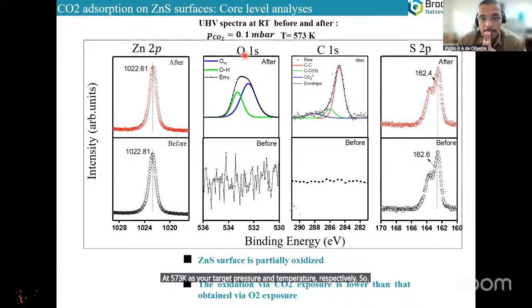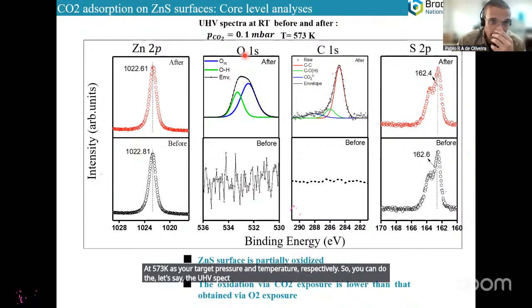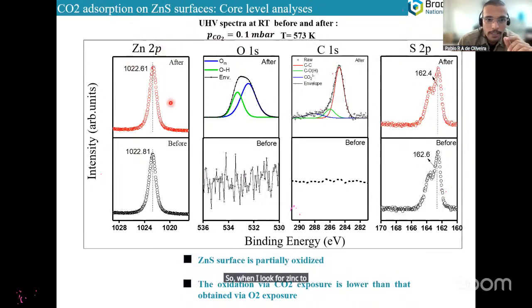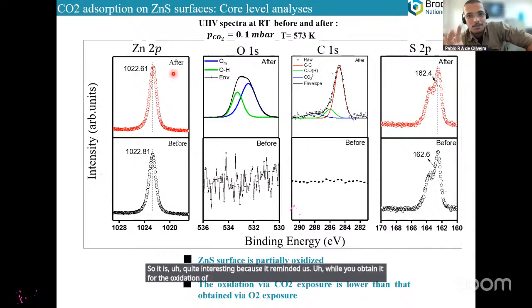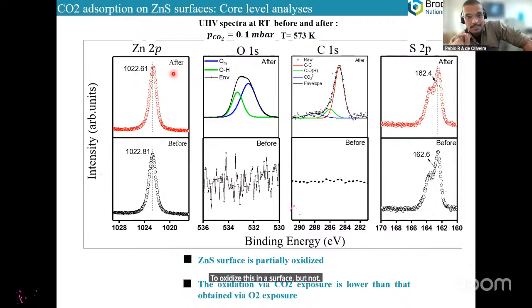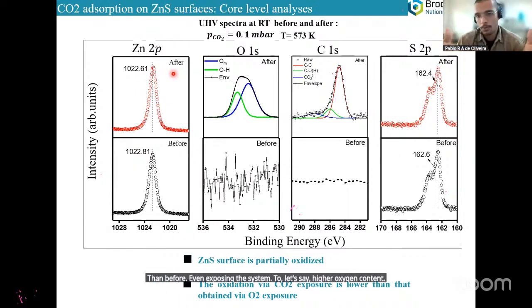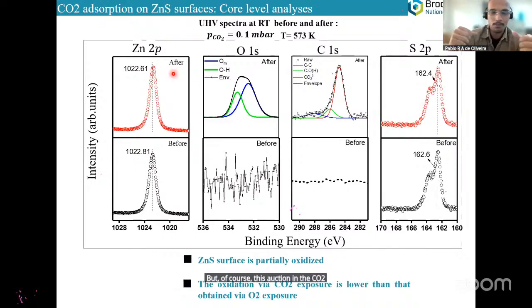So we can do, let's say, the UHV spectrum before and after analysis to highlight the modifications. So when we look for zinc 2p or sulfur 2p, we note a slight shift toward low binding energy. So it is quite interesting because it reminds us of what we obtained for the oxidation of ZnS. So basically, the CO2 might be used to oxidize the ZnS surface, but note that this oxidation is not that higher than before, even exposing the system to, let's say, higher oxygen content. But of course, this oxygen in the CO2 molecule is not free to move, and apparently it's not being dissociated.